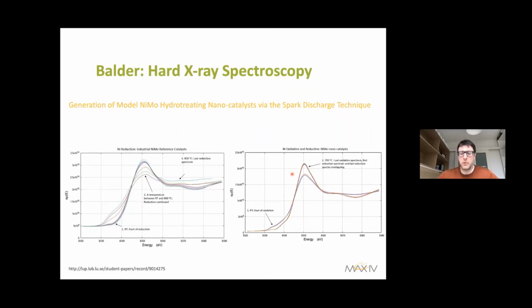This is a comparison of real catalyst on the left, reduction of real catalyst versus reduction of synthesized nano catalyst. And the difference is in one case, it reduces, that could be clearly seen from the absorption measurement, whereas the new catalyst that is synthesized by a specific method doesn't reduce. And this is done in the catalysis flow cell at 1 bar condition, as it's done typically in the plant.